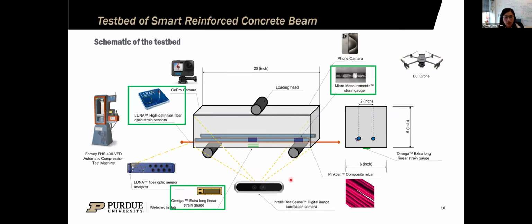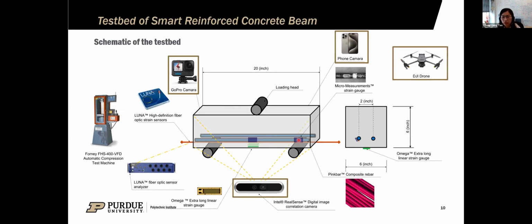And in addition to the smart sensors, we also have 4 image data collection devices, including the GoPro, cell phones, and drones, and also DIC cameras here. The design of the flexure test is based on the ASTM C293 standard with a total length of 20 inches and a span length of 18 inches. From the test bed, we are able to monitor and observe the material performance of the rebar and concrete in real time.